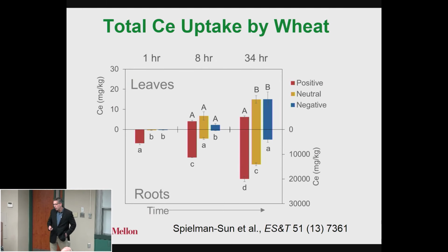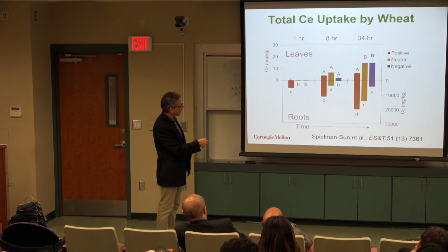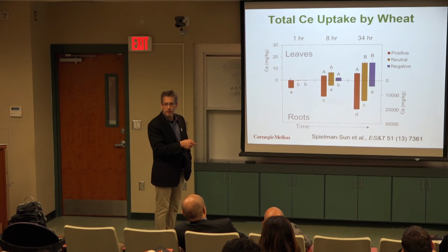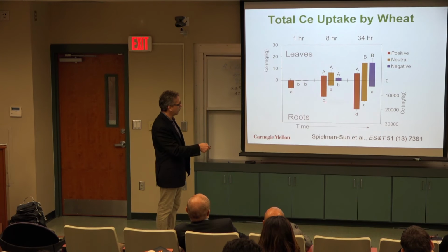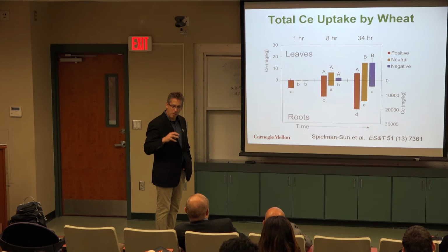When you do those exposures, you can measure how much cerium is on the roots of the plant, or above ground. So this is the cerium on the roots right away after we dosed, and this is over time. And then this is the concentration of cerium oxide in the leaves. Okay, so a lot of it is stuck to the roots. You can see these numbers. Some of it moves up into the leaves, and you can see these numbers are a lot smaller. So a small fraction moves up into the leaves, but some does.